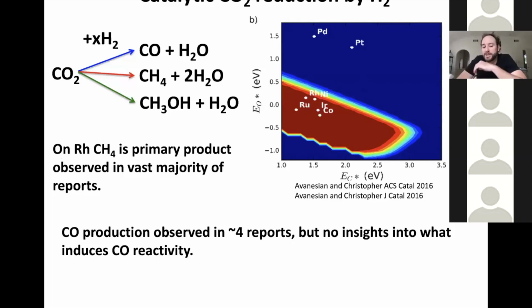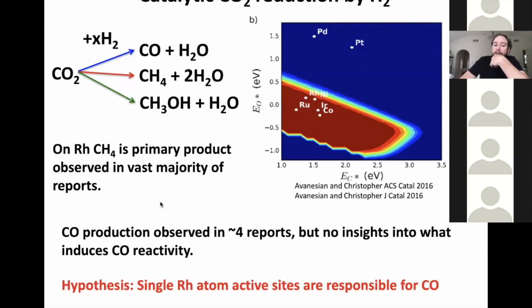There was a couple of reports, which I highlight here down at the bottom, that rhodium in certain ways, when you made it a certain way or pre-treated it a certain way or used a certain support, gave you high selectivity to CO, so a more mild reduction pathway, but there was really no insights into why. And our hypothesis was that maybe the catalysts that had been made here had relatively high populations of completely dispersed rhodium, and that those were responsible for production of CO, with the hypothesis being it may be challenging to do sequential hydrogenation processes on such a confined active site like a single rhodium atom.